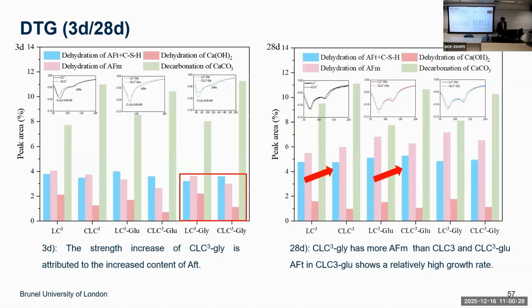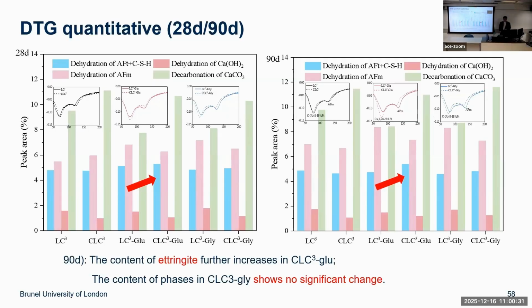So this one shows that, and we further quantify at 28 and 90 days. We have found a similar conclusion. So the AFt content at 90 days increases with the glutamic amino acid.